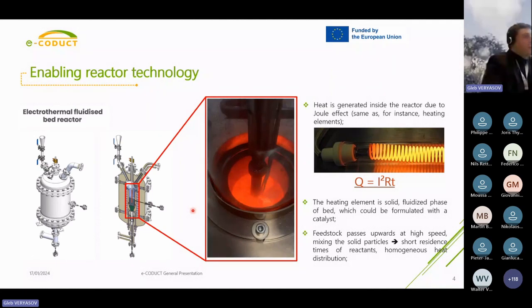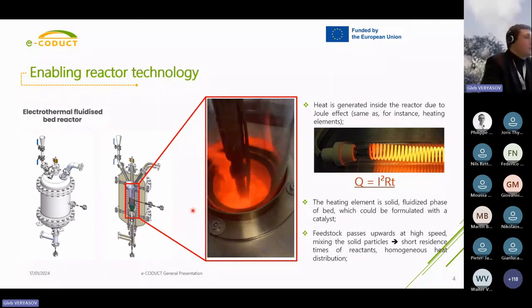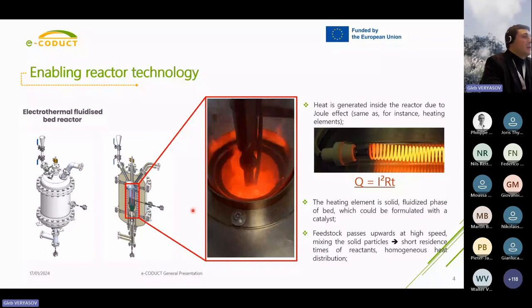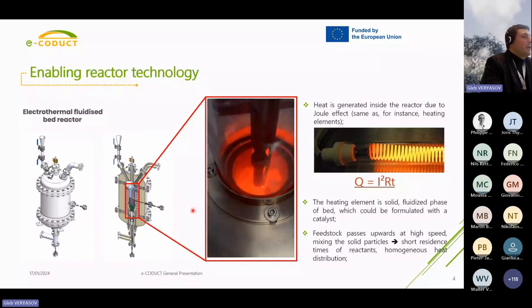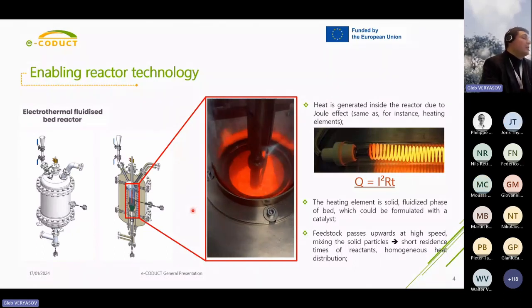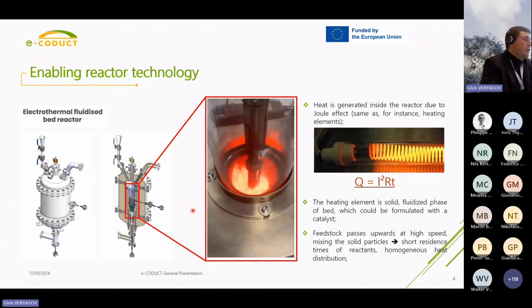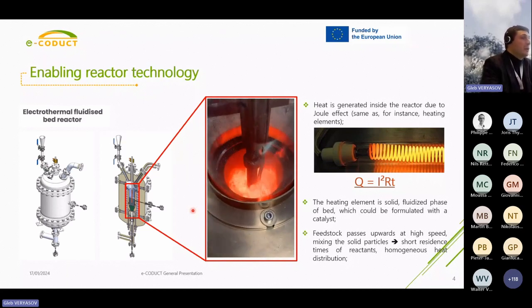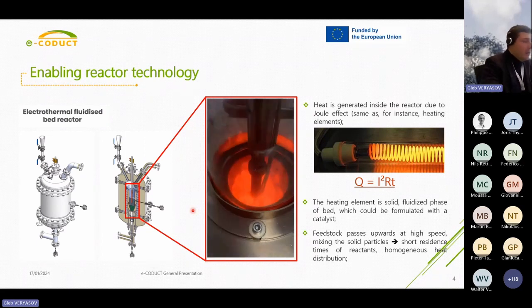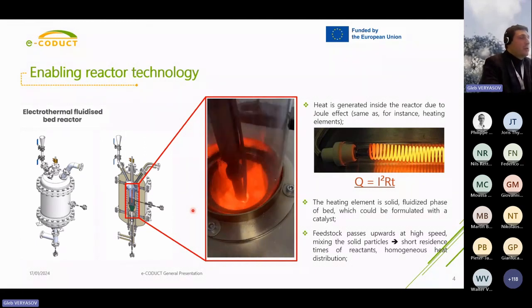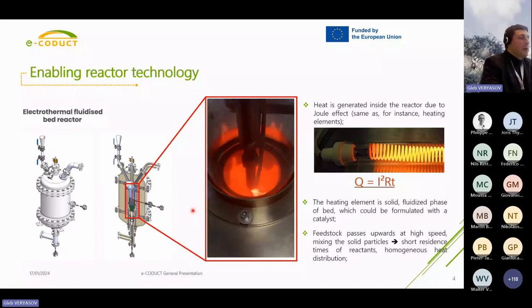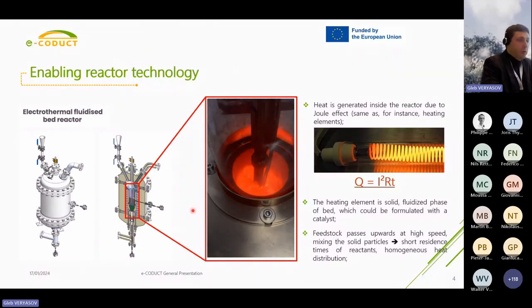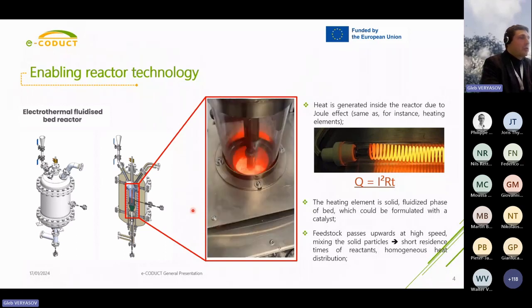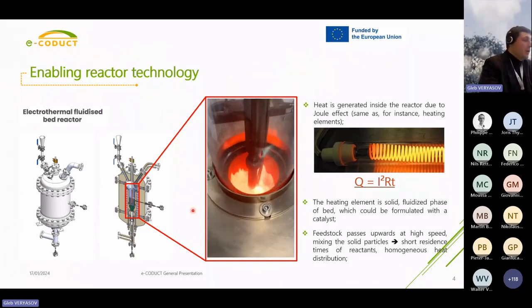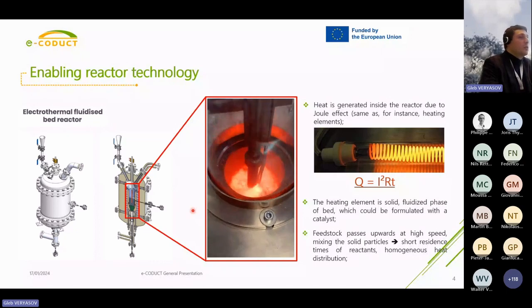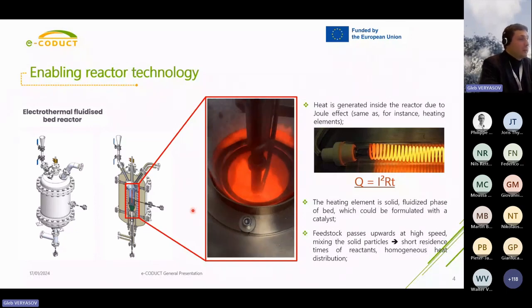The reactor is operated using the Joule effect. It means that it's the same as home appliances where we have a heating spiral, but instead of a heating spiral, we have a catalyst bed or fluidized bed where the heat will be generated right inside. As Walter has mentioned, in principle, this transformation in resistive heating is very efficient. So we also expect to reach high efficiency of the process thanks to use of this Joule heating effect.